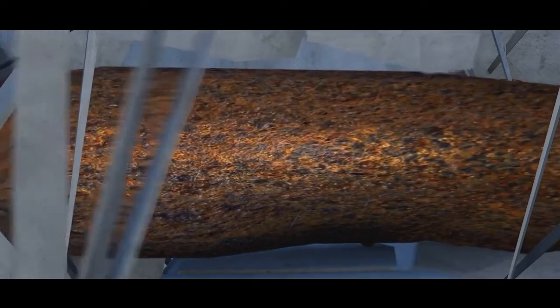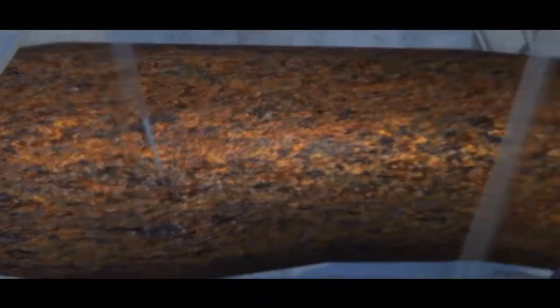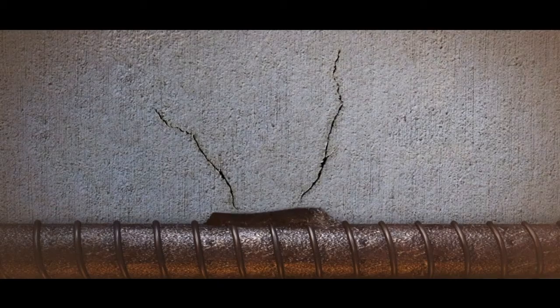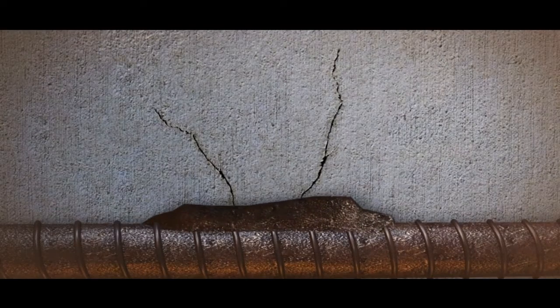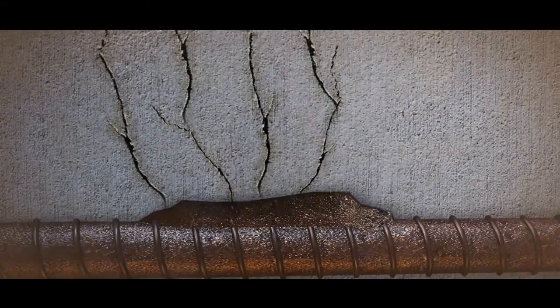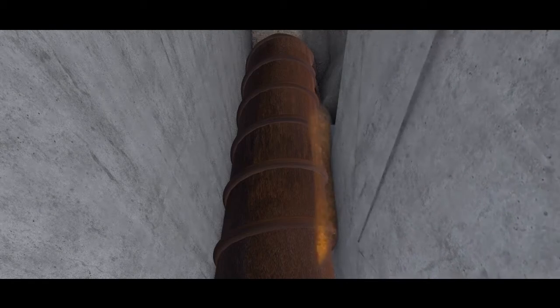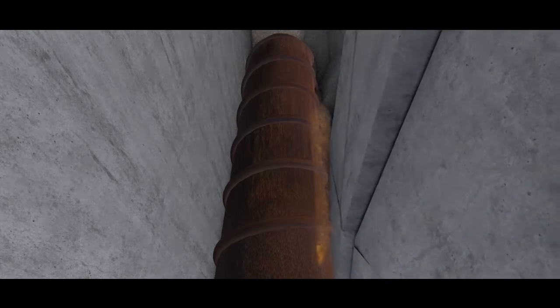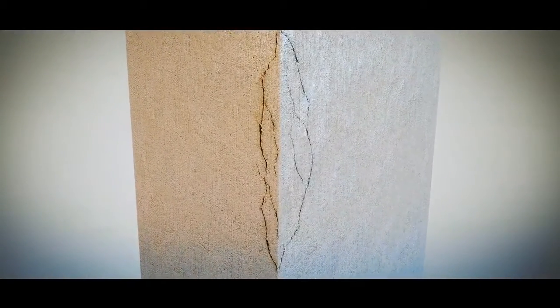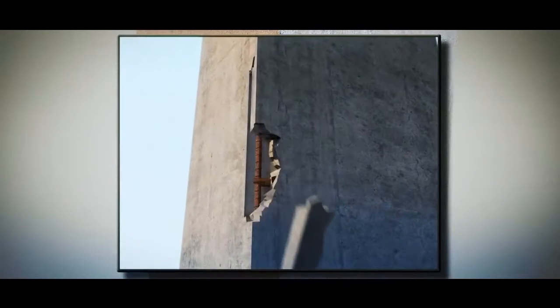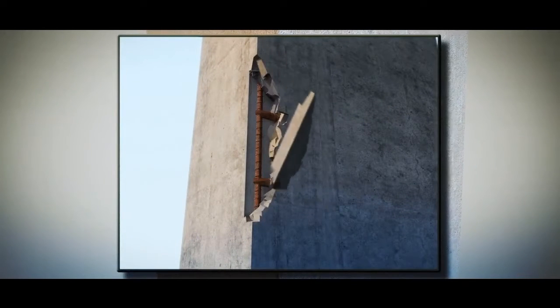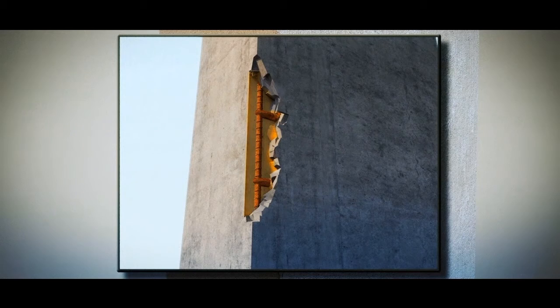These compounds have a higher volume than that of the original steel, expanding it several times in volume and creating substantial internal stress. While concrete has phenomenal performance under compression, it is very weak under tension. So these stresses induce cracks that allow further ingress of corrosive elements and accelerate deterioration. The corrosion product pushes the concrete cover and delaminates it, leading to concrete spalling and ultimately structural failures.